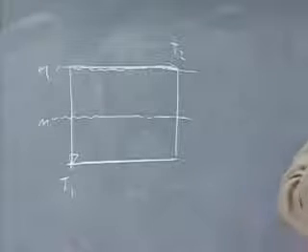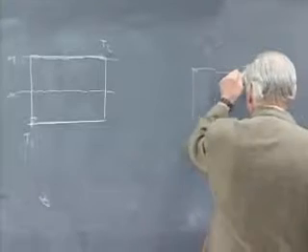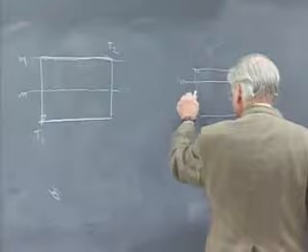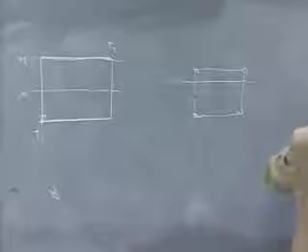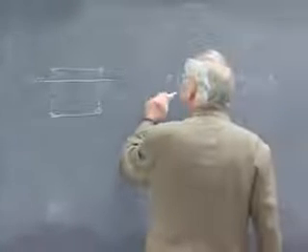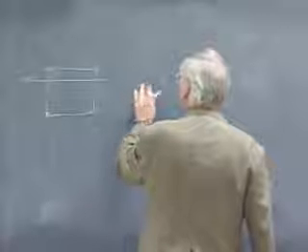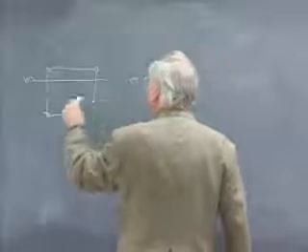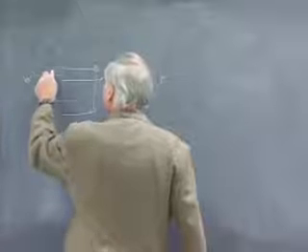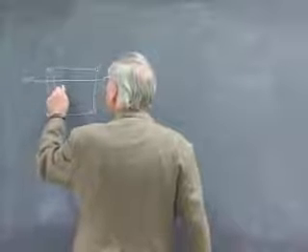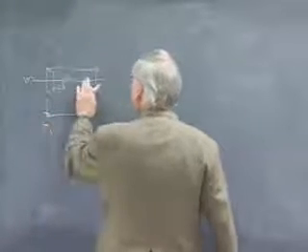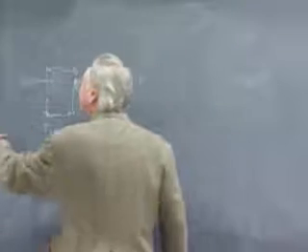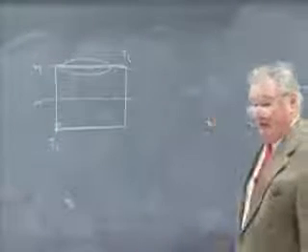Because if I have a mirror plane in space that passes in proximity to a lattice point, I can turn my theorem around and say that a translation T1 combined with a mirror plane, that is a reflection operation that's removed from the lattice point, I would have to introduce a new translation 2 delta, which is going to be incommensurate with T1. So I have to pick my third translation in one of two ways. Let me indicate that by drawing a circle. T3 can terminate anywhere over this mirror plane.